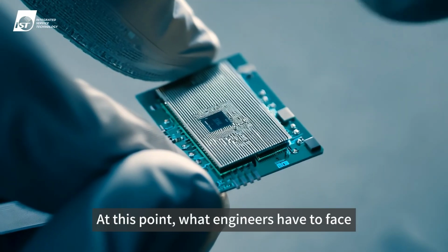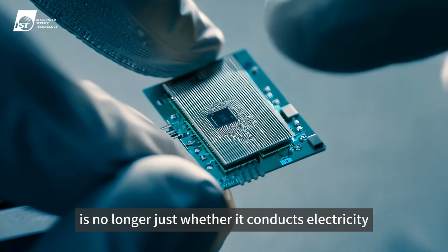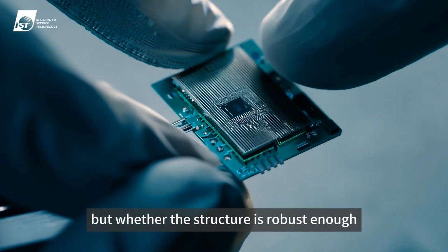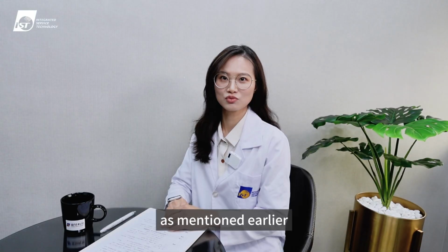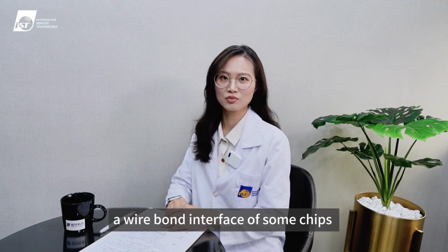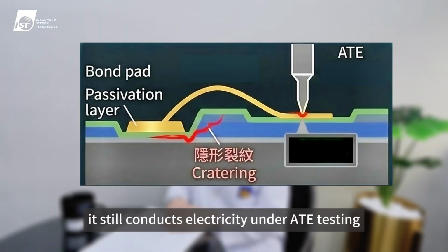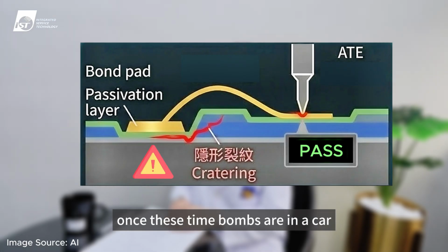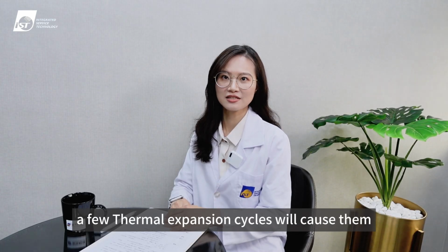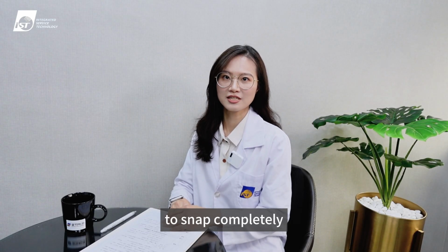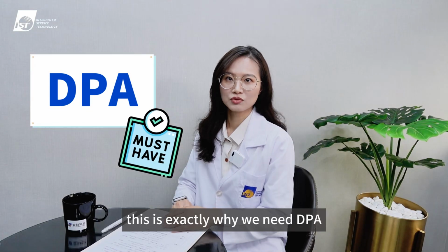At this point, what engineers have to face is no longer just whether it conducts electricity, but whether the structure is robust enough. As mentioned earlier, a wire bond interface of some chips might already have cracks. It still conducts electricity under ATE testing, resulting in a pass display. Once these time bombs are in a car, a few thermal expansion cycles will cause them to snap completely. This is exactly why we need DPA.